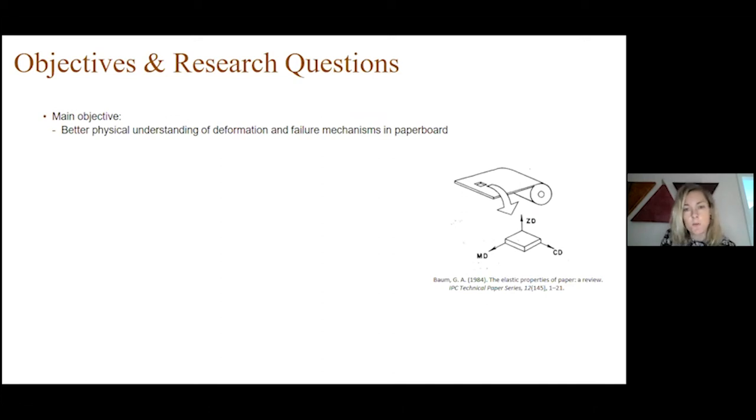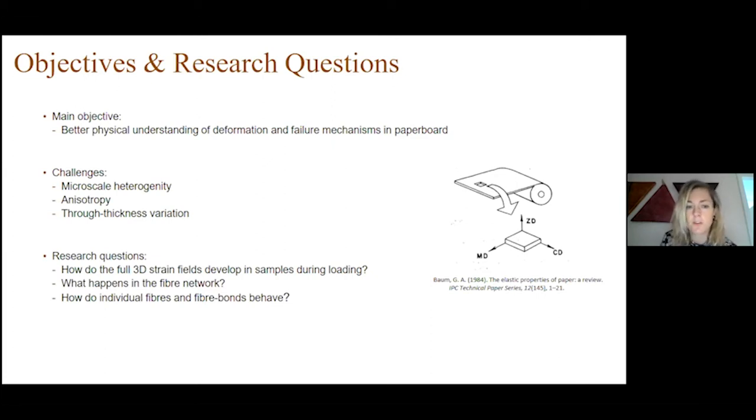The main objective of my part of the project is to obtain a better physical understanding of deformation and failure mechanisms in paperboards. The challenge with this material arises due to its microscale heterogeneity. The paperboard is built up by paper fibers and fiber bonds. The material is also anisotropic in the in-plane direction and we have a through thickness variation that depends on how the paperboard has been manufactured. Some of the research questions I work with is to study how the full 3D strain fields develop in a sample during loading and also to move down at lower scales and see what happens in the fiber network during loading.